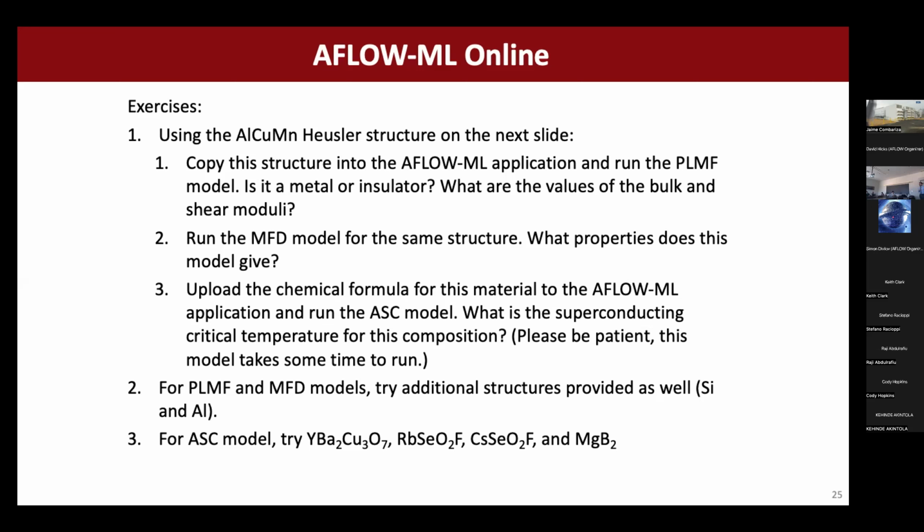But I would say the most important thing about these big databases, which is often missed by some people, is that it really needs to be consistent. So for all the calculations here, we have what's called the AFLOW standard for how we run our calculations. It's a very strict set of guidelines for what parameters we use for each calculation. And if everything is done consistently, that's a nice environment for machine learning or for data analysis or the like. As long as you have a consistent set of data, the trends are going to be there generally.